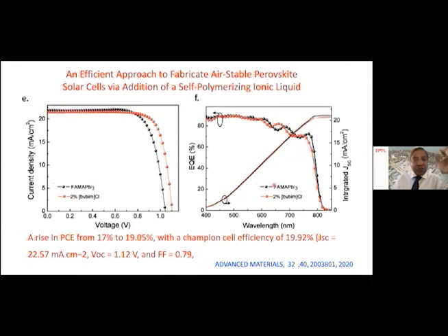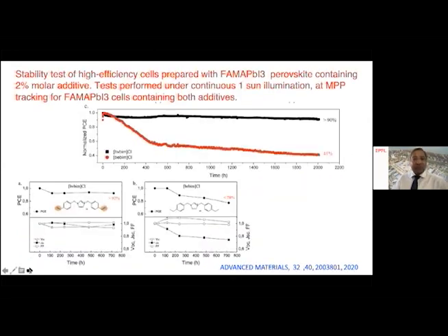So the beauty of this ionic liquid having double bonds is that when you heat it, it forms a self-polymerization around the perovskite at the grains. So these are the two examples which I have taken just to demonstrate how one can really improve the stability of the perovskite compositions by selecting functionalized additives.